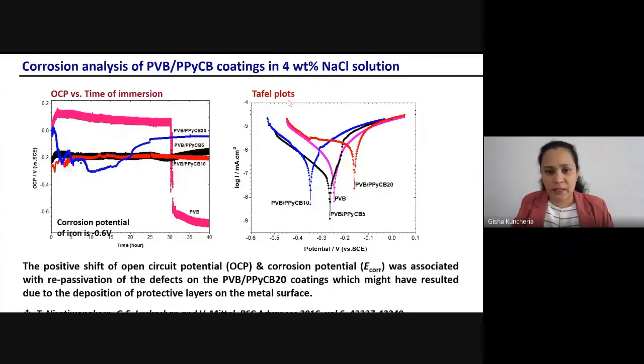Coming to the Tafel plot, this is the Tafel plot. It's log corrosion current versus corrosion potential. So here also you can see the corrosion potential of the conducting polymer coating is towards the positive side compared to the pure PVB coating.